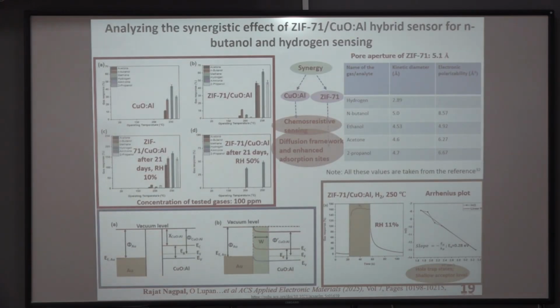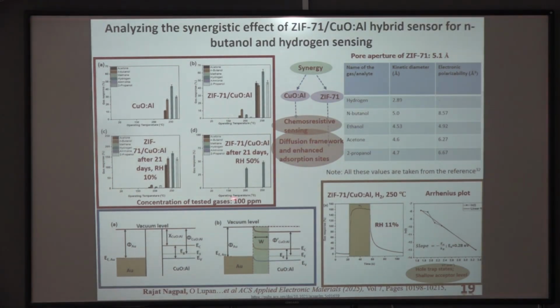Now coming to the application part, sensing performance, here we can see going from bare metal oxide to ZIF-71 hybrids, appreciable selectivity for n-butanol is observed, which was not the case for bare metal oxide, and at high temperatures, hydrogen sensitivity is retained even after 21 days of measurement. But at the high relative humidity test, we can see there is diminished sensing response for VOCs, and it retains sensitivity only for hydrogen. Why is it so? We will see in the subsequent slide. And here it confirms the synergistic effect of both components of the hybrids.